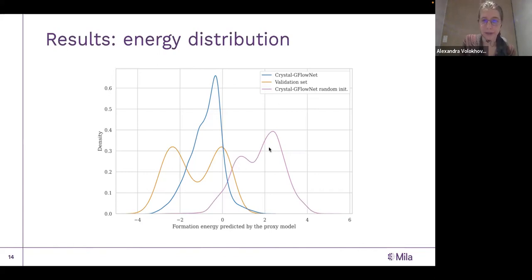And we see that once GFlowNet is trained, the distribution of energy moves quite a lot towards the negative energies, which is physically meaningful. And also it doesn't coincide with the validation set, but it is not expected to perfectly coincide with the validation set, because as I said, the trained GFN should sample from the distribution defined by the reward function, but the validation set for the proxy model is not necessarily sampled from this distribution. So we do not expect these two plots to coincide, but it makes sense that the range of the samples moves towards the validation set.